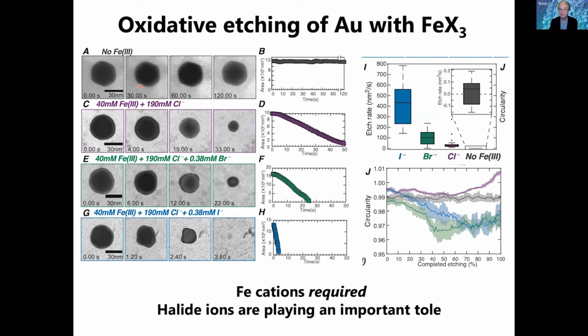Clearly, some kind of redox couple corresponding to an inorganic species like an iron is essential to etching the gold and to making that a possibility for it to occur. And what you can also see here is that if we change the halide ion from chloride to bromide to iodide, the etching speeds up enormously. In fact, so much so that if you look here at the iodide case, you can see very clearly that the etch rate is so fast that it starts to peel off multiple layers of the crystal all at once. It becomes a very rough particle. It's kind of entered into a roughening regime etching mode when we've really got the fastest etching in the presence of the iodide.